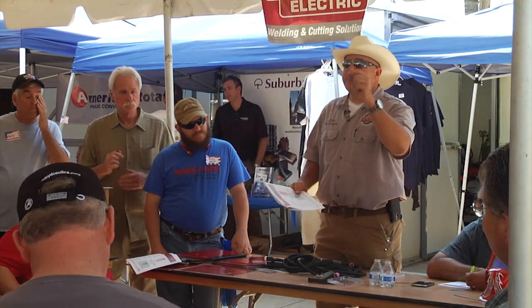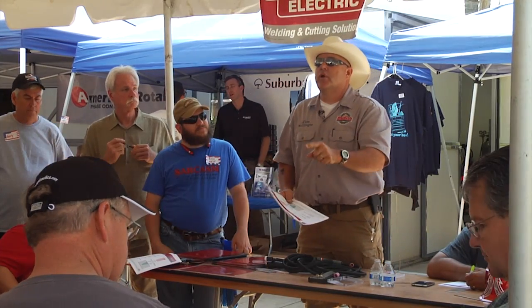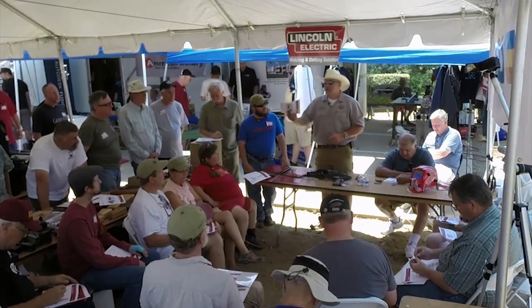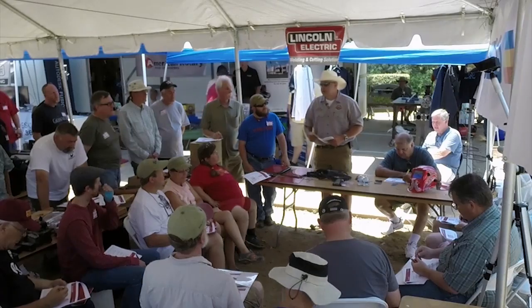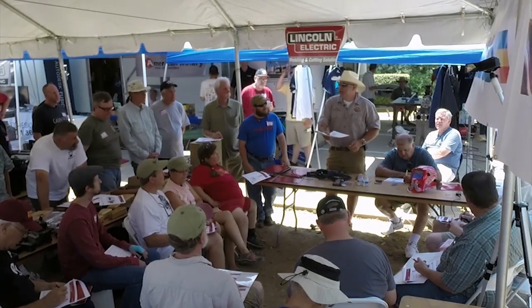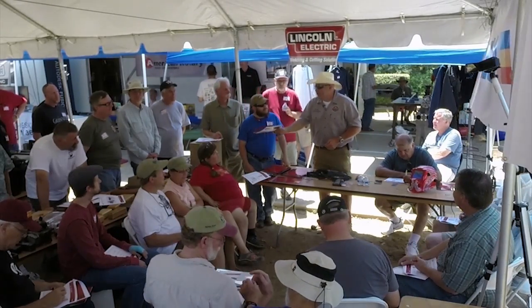That same equation, let's flip it on the backside. This becomes very important in a minute. How hot is the electrode? 3,000 degrees. What temperature did I tell you that tungsten melted at? 6,280 degrees. So we don't melt our tungsten.